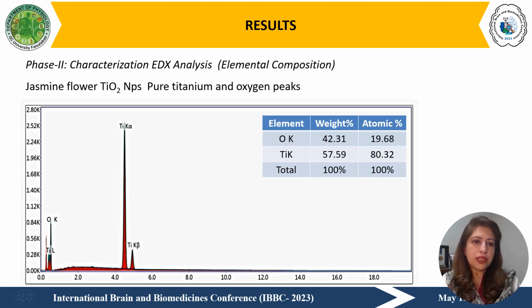The energy dispersive X-ray spectroscopic analysis was carried out to calculate the elemental composition of these titanium oxide nanoparticles synthesized by the jasmine flower extract. These titanium oxide nanoparticles were having the pure peaks of titanium and oxygen, displaying no impurity in their formation.